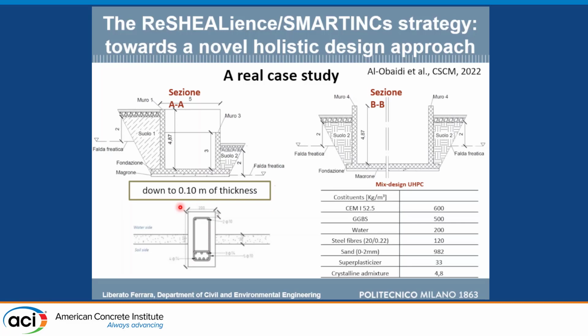to 10 centimeters. So it's true that mixed design is completely different, but it's also true that you use much less material. There is another important thing to take into account in the metrics. When you look at this mixed design, the steel fibers are already in the mix. So they count as a burden or as a cost voice for the cost per cubic meter of the material. When you have ordinary reinforced concrete, the reinforcement has to be taken separately, but you have to evaluate them both in order to have a complete picture.